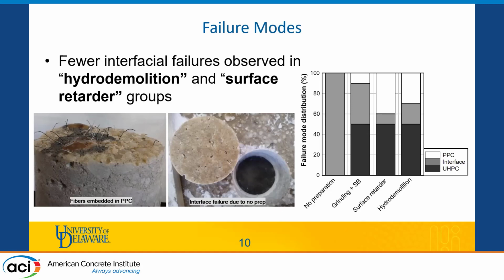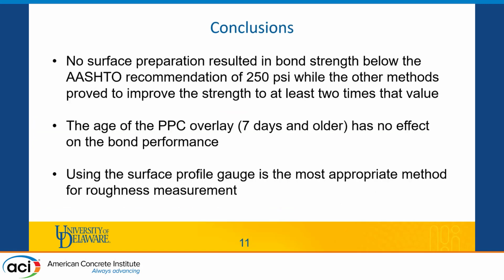We can also see here that the fibers exposed for both the hydrodemolition and surface retarder contributed to the interface by being embedded into the PPC that we see here, which is an interesting thing to see. And we can probably see that only the fibers that were in the direction of the core contributed to this, and still it's a good thing to see.